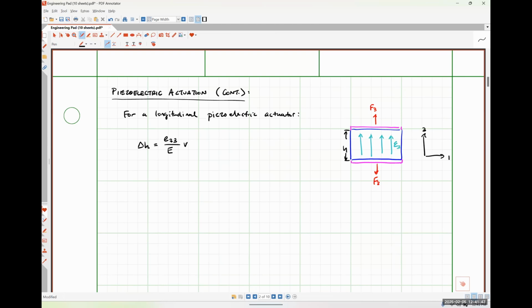However, there is a caveat to that, and I think this is where the confusion was coming from. So we need to remember that a piezoelectric material is in itself a polarized material, which has some charge asymmetry. So essentially, we need to make sure that the positive polarity terminal of our voltage is on the positive polarity terminal of the charge asymmetry of the crystal itself in order to generate that positive change in displacement. So the poling of the piezoelectric crystal is going to tell us which polarity of voltage is going to make it expand and which polarity of voltage is going to make it contract.